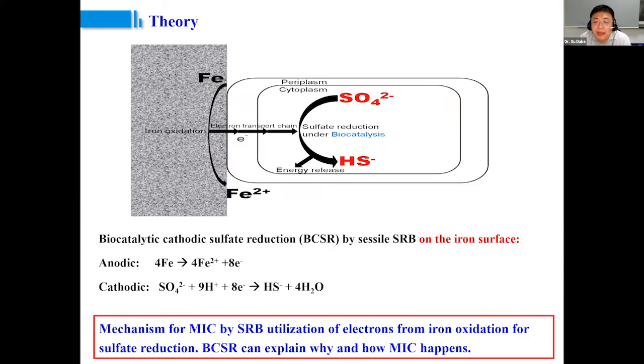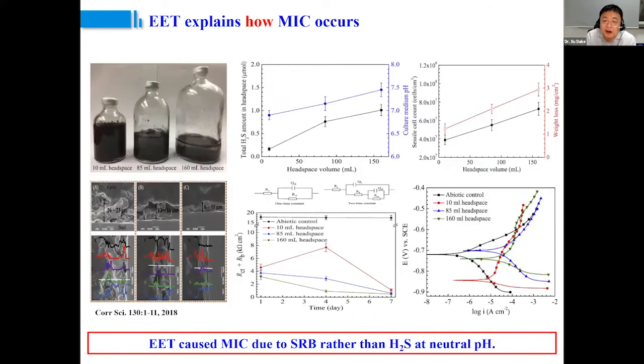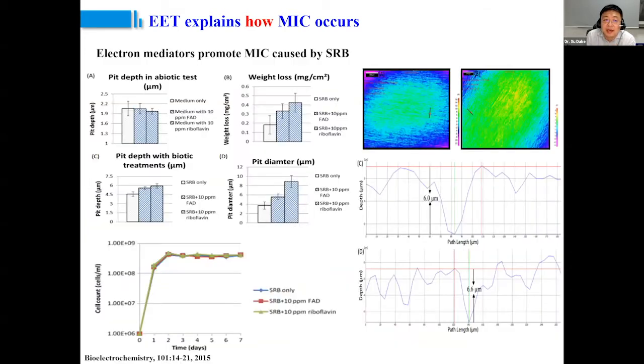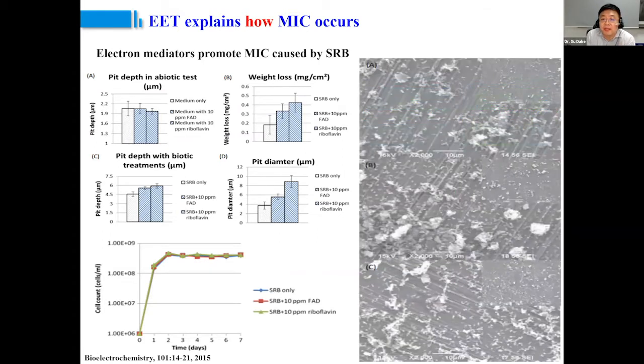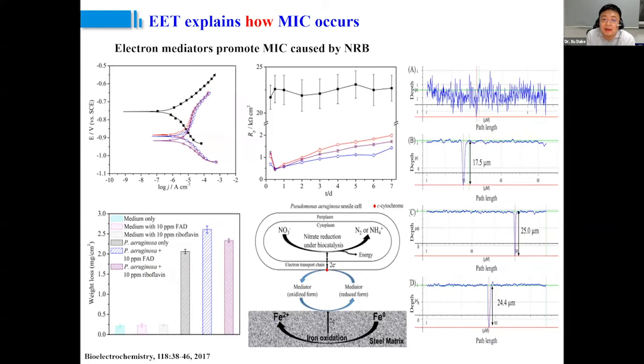And we make a proposal mechanism for SRB. We think the electrons are taken up by SRB via the electron transport chain and result in MIC. And we also verify that the corrosion caused by sulfate-reducing bacteria is mainly due to EET rather than the biogenic H2S at neutral pH. This is published in Corrosion Science. And we also tested that electron mediators will accelerate corrosion by SRB, and even promote MIC caused by NRB.